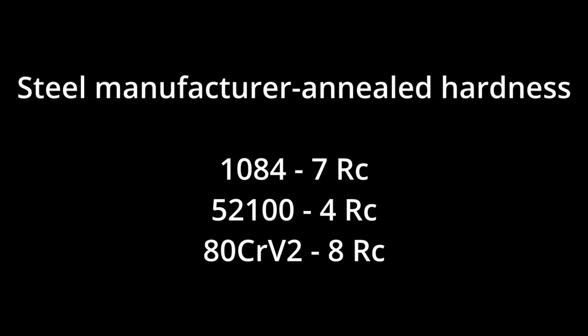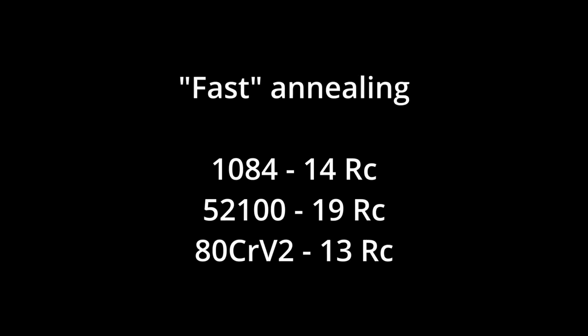The steel manufacturers typically want the steel to be as soft as possible for easy machining and grinding by the end customer. The very soft steel is achieved by having a relatively coarse annealed microstructure. If instead the carbides are smaller and the steel is a bit harder in the annealed condition, then the hardness-toughness balance can be improved somewhat. By modifying the normalizing and annealing process, called thermocycling by knife makers, you can achieve these results.